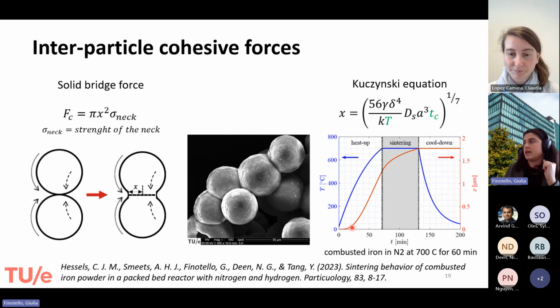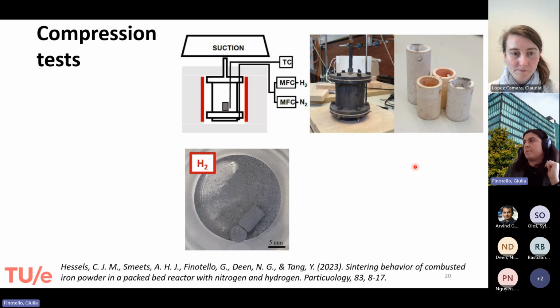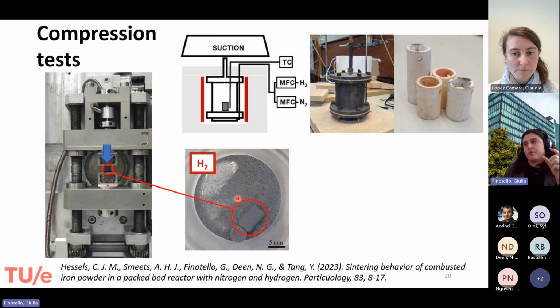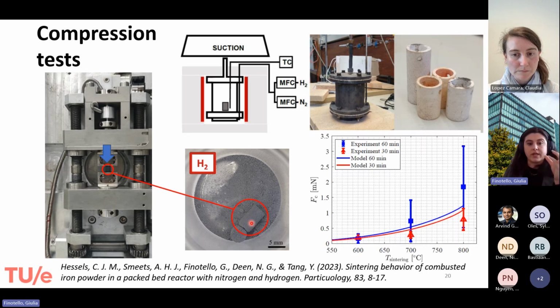And you can already see here that the neck is growing when you are increasing the temperature. So what we did was to make some sample in a crucible and let it sit under hydrogen. We did also nitrogen, but under hydrogen we let the particles sinter together, and then we did a compression test. So we correlated the force that was needed to break this sample, and that was a measure of our cohesive force.